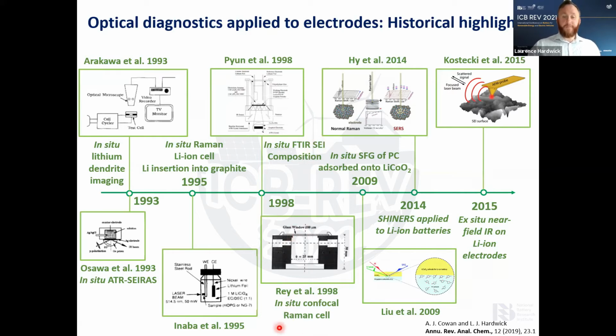And the Raman technique was further developed in this demonstration of using a confocal Raman cell, so you could then begin to get some spatial resolution on the electrode surface. More, say, exotic techniques such as sum frequency generation looked at the absorption of propylene carbonate onto a lithium-ion positive electrode, a lithium cobalt oxide. A variation of surface enhanced Raman, which I'll discuss in a lot more detail, with the acronym SHINERS, and we'll see what that acronym stands for, was applied to battery electrodes, particularly on silicon, looking at the formation of the solid electrolyte interface on silicon electrodes.